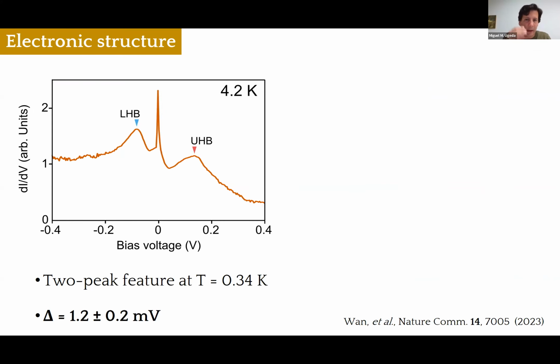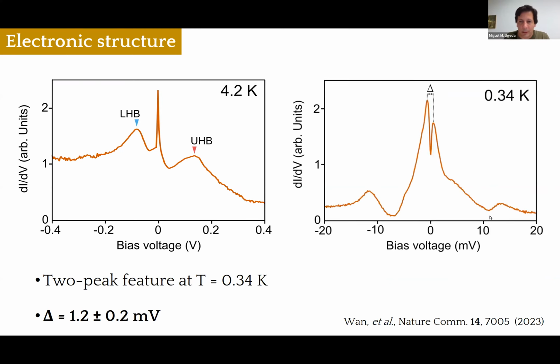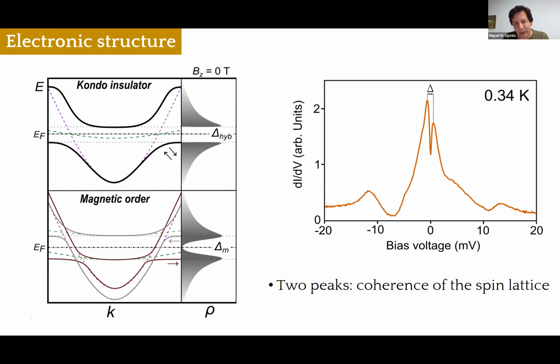Here I'm showing you again the dI/dV at 4 Kelvin. So if we now cool down to 300 millikelvin, which is the base of our STM setup, basically we observe, as expected, the split of this Kondo resonance into two peaks with an average distance between the peaks of 1 millielectron volt. Okay, so this is something that is expected.